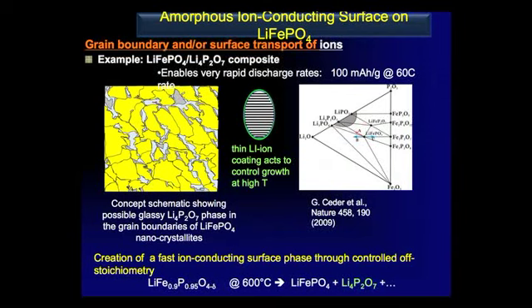But effectively, the process relied on the fact that if you take this iron phosphate, which is slightly substoichiometric in lithium, and you heat treat it gently, you phase separate out an iron pyrophosphate, and that material is quite subject to further reduction to FeP. So on the old Ellingham, on the carbothermal reduction diagram, this is more prone to reduction than is this. So it reduces and this does not, and it basically casts out this material on the surface of the iron phosphate. And so this led to what we consider to be a new area of surface transport of ions. And more recently, Gerbrand Ceder has used a rather similar technique to cast out a lithium ion conductor on the surface, which is lithium pyrophosphate.